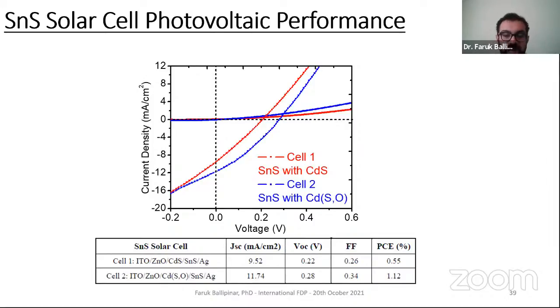Basically, the efficiency is still lower than the highest record. We had the motivation, and we developed a new technique. There were many challenging points that need to be addressed to reach higher efficiency in this emerging photoabsorber material. But we prove this point: there is definitely an improvement in cell two, which has cadmium oxysulfide as the N-type layer. So cadmium oxysulfide helps to improve the efficiency and all the solar cell photovoltaic parameters: short circuit current, open circuit voltage, and fill factor as well.